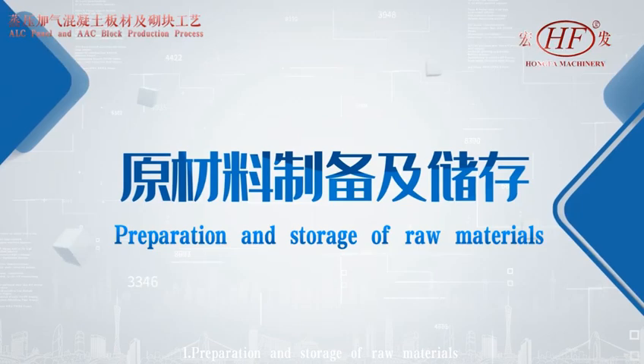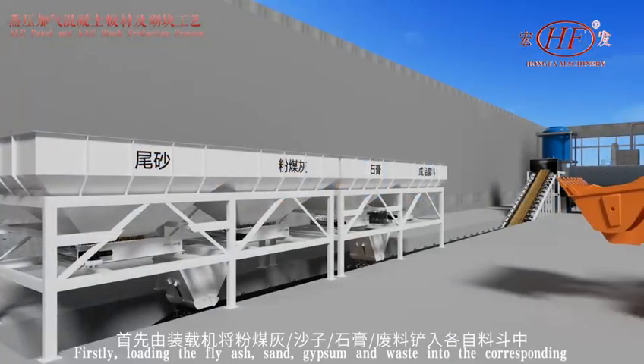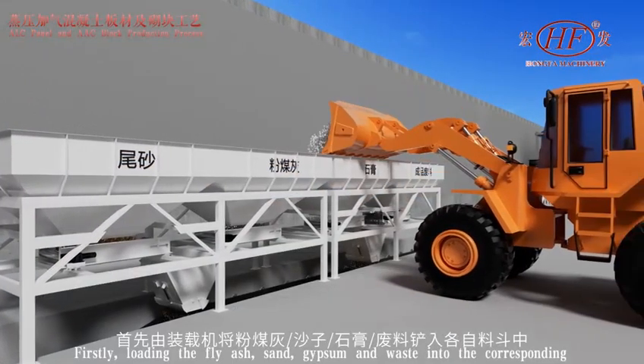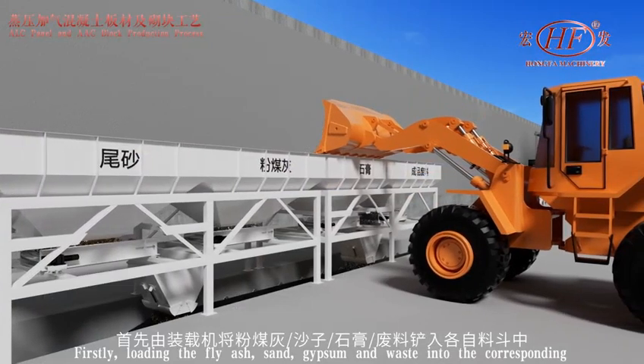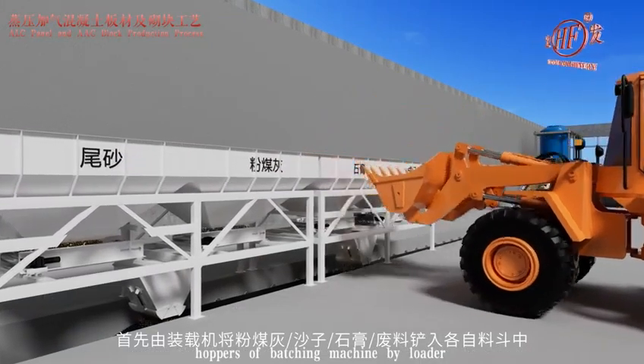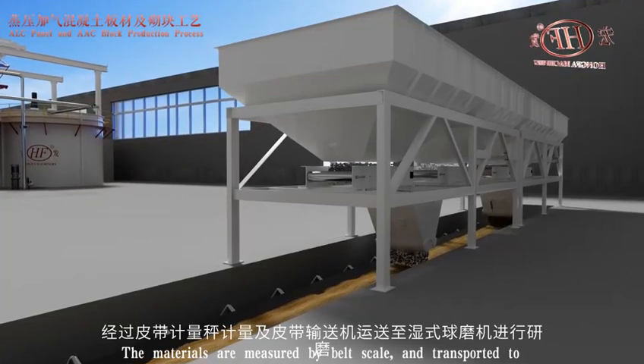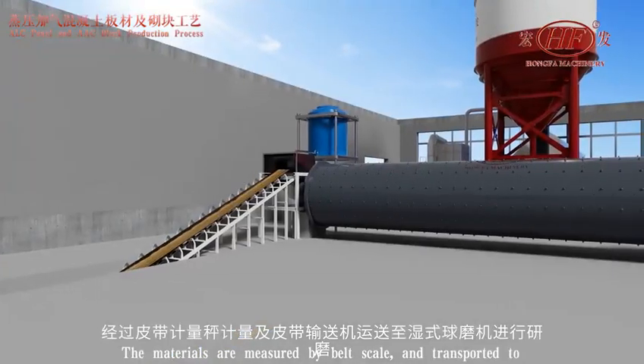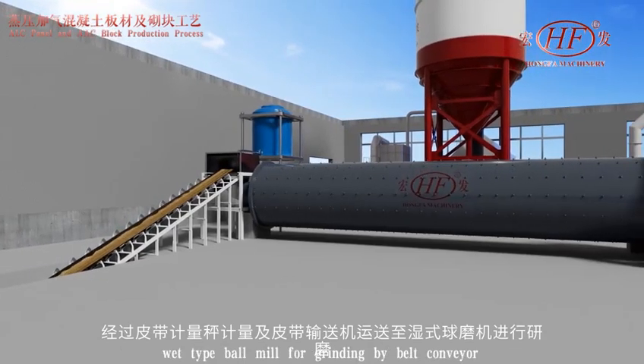1. Preparation and storage of raw materials. Firstly, loading the fly ash, sand, gypsum and waste into the corresponding hoppers of batching machine by loader. The materials are measured by belt scale and transported to wet-type ball mill for grinding by belt conveyor.